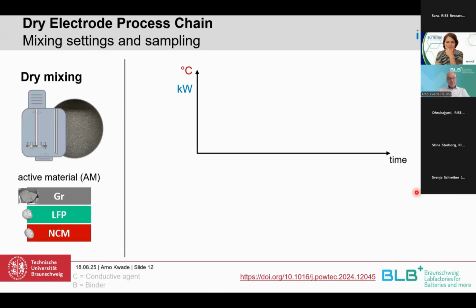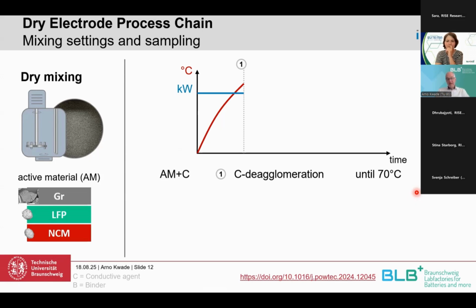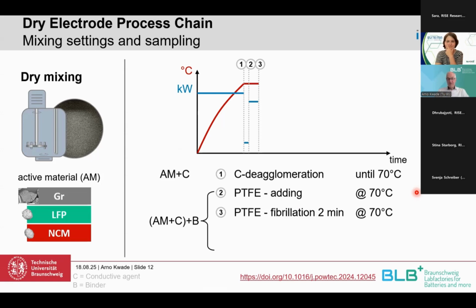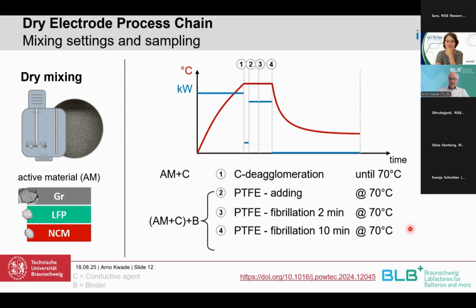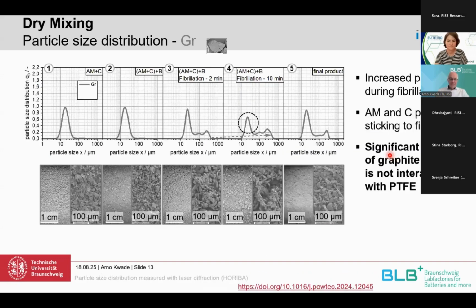Now having a look at our batch mixing process using an Eirich mixer usually, then you see that we have a deagglomeration, first of all, of the carbon black at the beginning and also heating up the mixture. Then we're adding the PTFE, and now we are starting to have a fibrillation of the PTFE for 2 minutes and then for 10 minutes, but it's all showing that we take some samples. And at the end, we have the, let's say, finishing and homogenization of the material, which is necessary to have the right granule size for the later film formation.